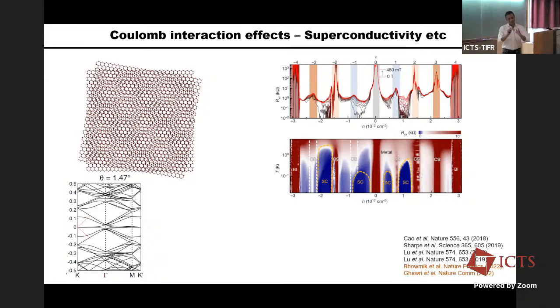But now, with our ability to put them together, we can put them in a slight angular mismatch, through which you can engineer band structures where the electrical bands are extremely flat, and that leads to a completely new set of physics. For example, it leads to strong insulating phases at certain filling of these bands, and that's called the Mott. Those are supposed to be Mott insulating phases.